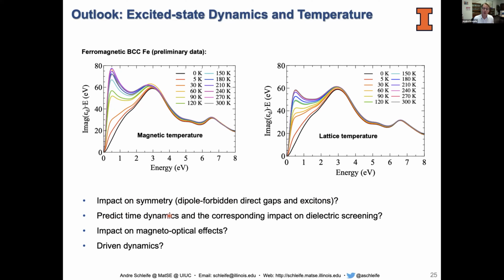Explicitly, I mentioned this earlier, we want to predict the time dynamics of these equilibration processes, either through improvements to time-dependent DFT, or maybe by coupling it to approaches like the Boltzmann transport equation. And we want to connect that back to the screening, right? If you do this in a doped material versus a non-doped material, the screening changes, as I told you earlier, and that will impact this equilibration dynamics, because the screening changes the electron-electron interaction.